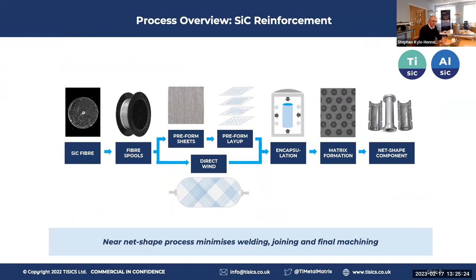How do we make it? We make silicon carbide fiber in our factory in Farnborough. Despite the fact it's a ceramic, we can get enough flex in it to wind it into different shapes. We've got a technology that allows us to filament wind by pre-coating the fiber with aluminium, in this case, or titanium. We encapsulate it into a near net shape mold and use hot isostatic pressing to diffusion bond and combine the fiber and the aluminium and any other features to give us a matrix that is a uniform distribution of our fiber in there. And as I say, net shaped parts, as you can see.